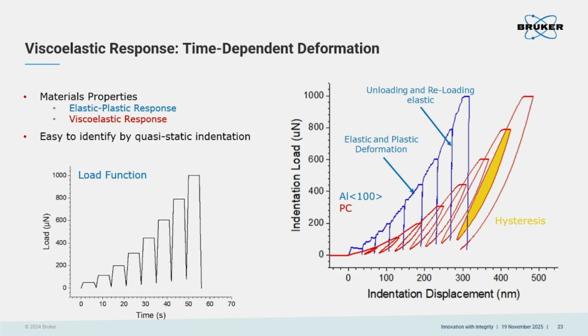So if we take a look at the unloading and the next reloading curve collected from polycarbonate, you will find it is very interesting because they do not overlap very well. This is the unloading, and then reloading goes along another path to the next cycle. Unlike aluminum, where you can see there is almost 100% overlap between unloading and reloading. So that is very strong evidence, a very good observation point for us to judge the speed sensitivity of our polymer samples.